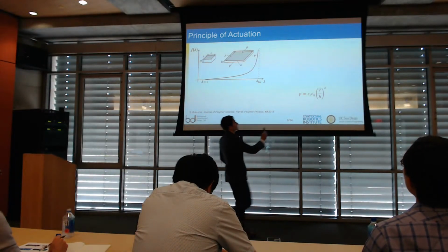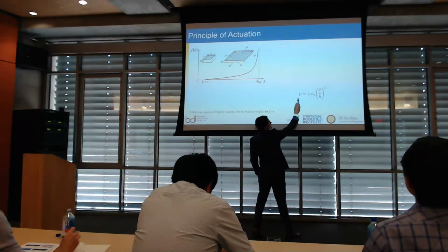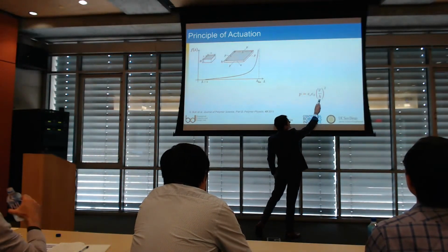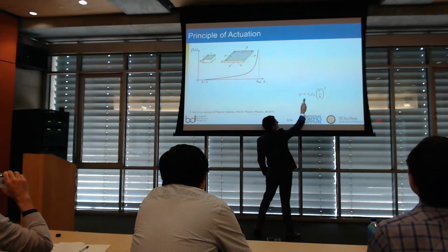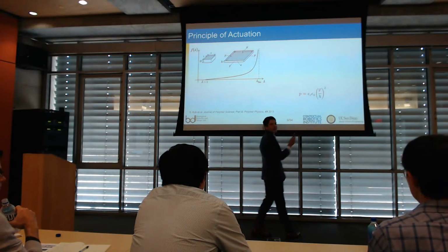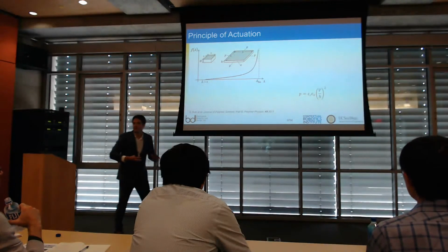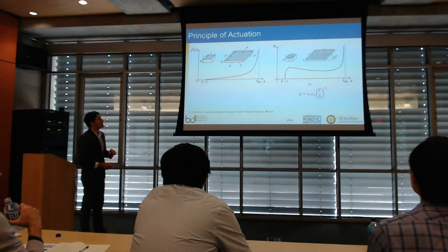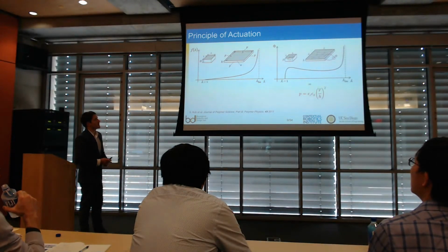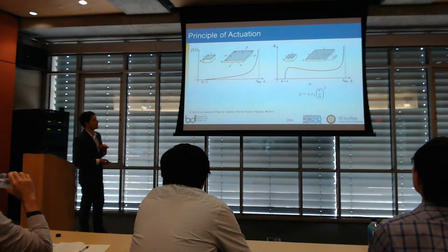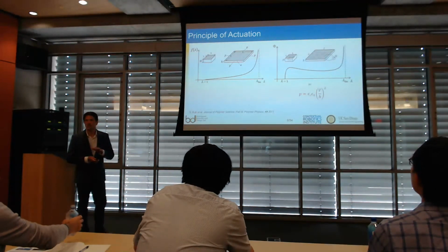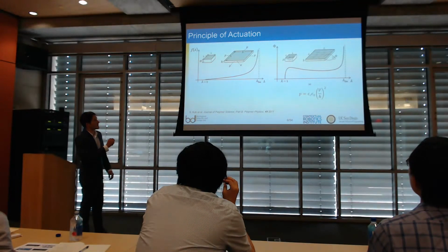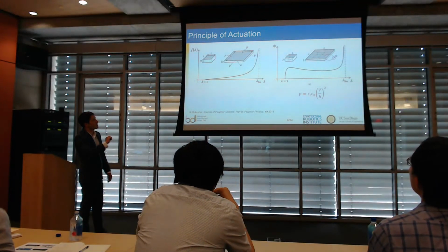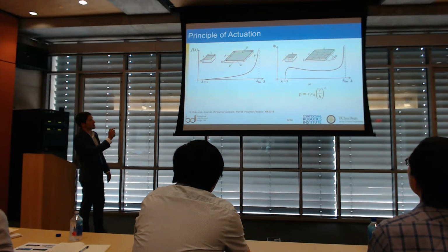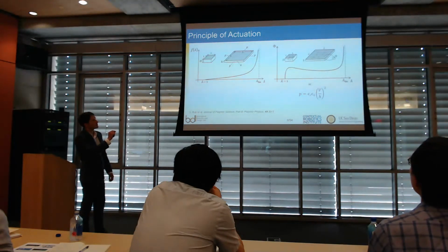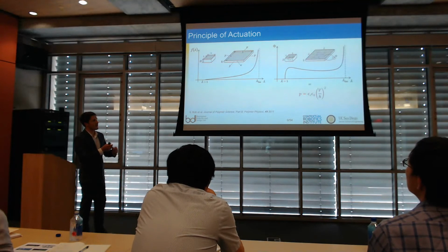So if you apply a constant voltage, you're generating a pressure, which makes the thickness thinner, which then increases the pressure, which then decreases the thickness even more. So you're generating this positive feedback loop. And so then the curve, if you plot the voltage as a function of the stretch of the material, looks more like this. So it takes a certain amount of voltage to get it to deform a little bit, and then after a certain point, it'll start feeding back.